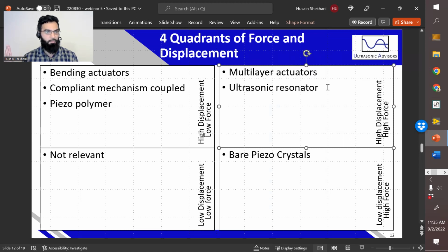I mentioned that we have 0.4 microns of displacement when we apply 1,000 volts. However, using ultrasonics in a resonance format and also providing a specific shape to your device, with the additional components added, you can increase your displacement by up to 1,000 times. So now you have 400 microns of displacement instead of 0.4. Usually you get up to 100, which is typical in some applications, but you can get up to 400 microns, or half a millimeter, of displacement. And you provide a particular phenomenon that you're going after, like cavitation or welding or cutting. Now you suddenly have a very effective device.